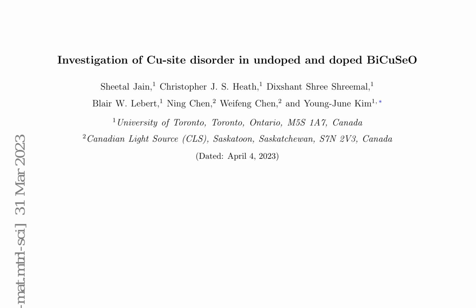This study presents a comprehensive analysis of the structural and dynamical properties of undoped, Ag-doped, and Pb, Ag dual-doped BiCuSeO, using X-ray diffraction, XRD, and extended X-ray absorption fine structure, EXAFS, measurements. Key findings include the unusually large isotropic mean square displacement of Cu in undoped BiCuSeO, observed in XRD results, and large atom pair mean square displacement values along Cu-Ag and Ag-Cu-Ag in all samples, revealed by EXAFS. These observations collectively indicate significant intrinsic disorder in the Cu site of BiCuSeO, retained upon Ag doping.